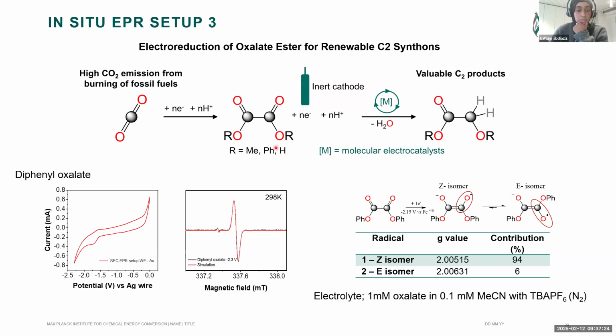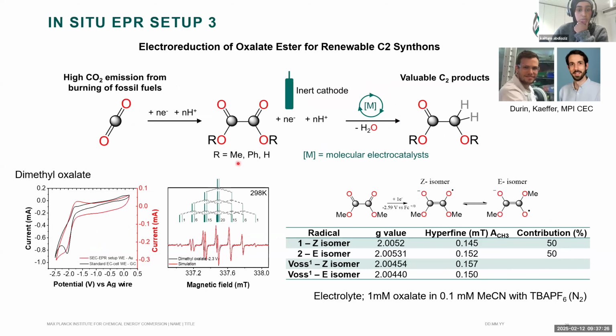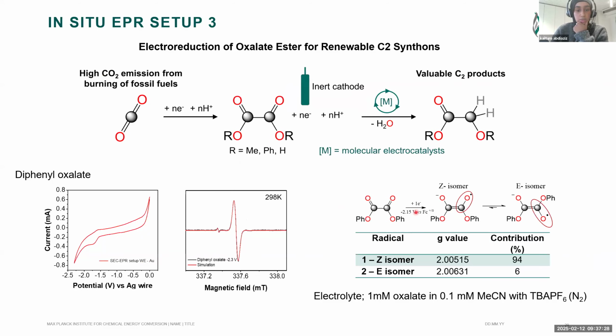And then we went on to a variation of the complex. So that was 2 methyl groups, and here we then worked with 2 phenyl groups. And similarly, we did the exact same experiments, and we saw that we have 2 different species. However, one in majority at 94%, and then the other one at 6%. And we think it's this E isomer due to the steric hindrance.